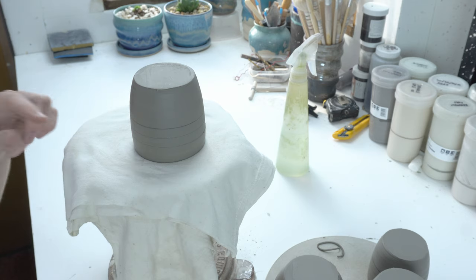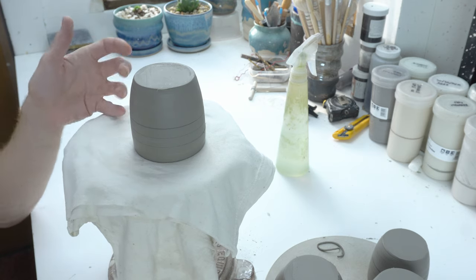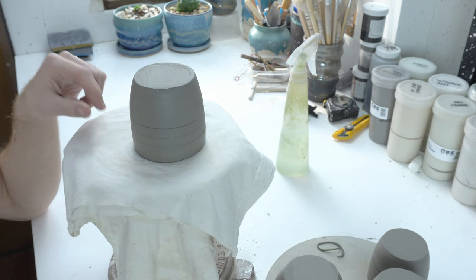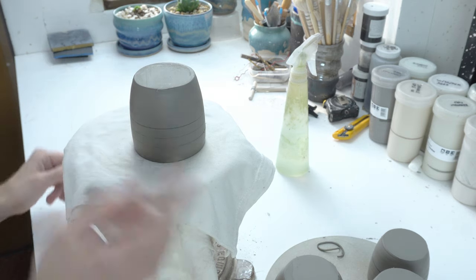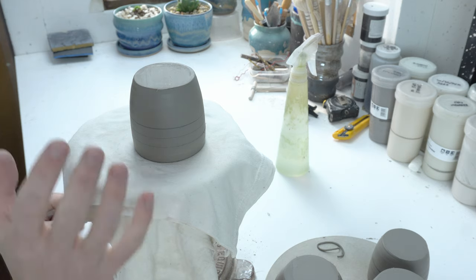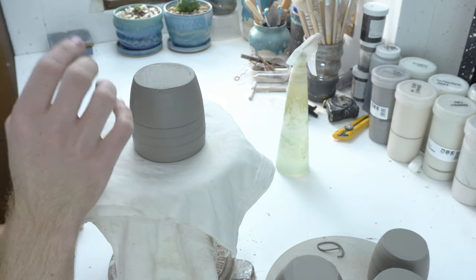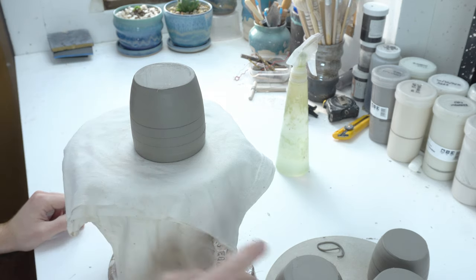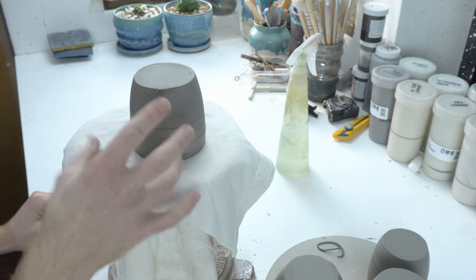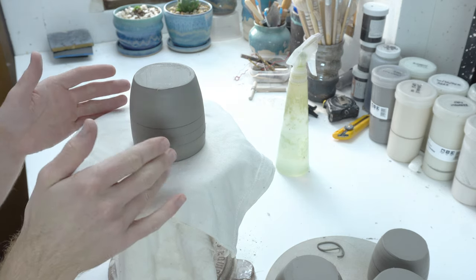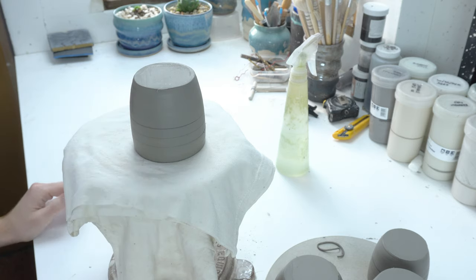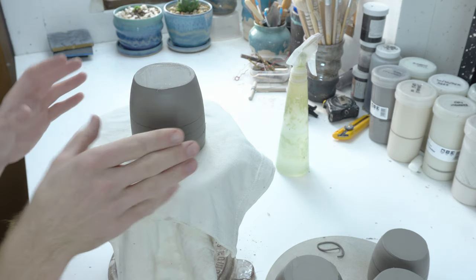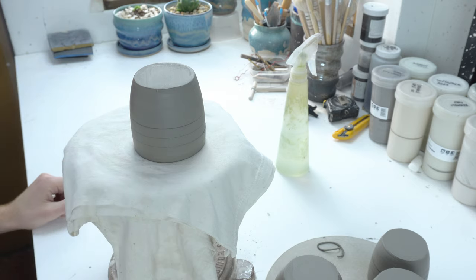What I've actually done here is thrown them two days ago, wired them off, so trimmed the outside and wired them off. I've got a video on that, I'll try and remember to link in the comments. Then put them upside down to dry overnight. The reason you put them upside down is because you want the outside drier than the inside ideally. So if you dry them upside down it kind of traps the moisture inside a bit more. You definitely don't want it the other way around.